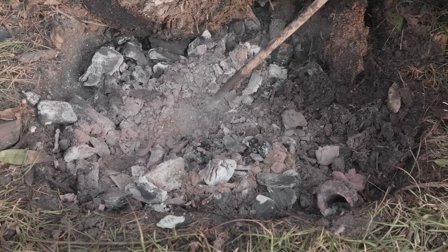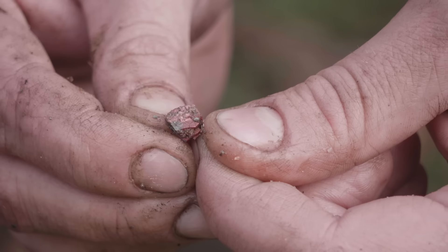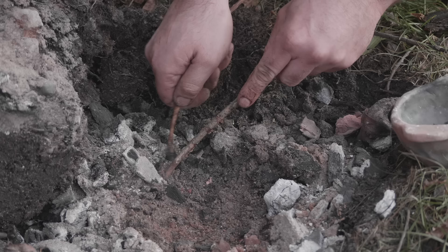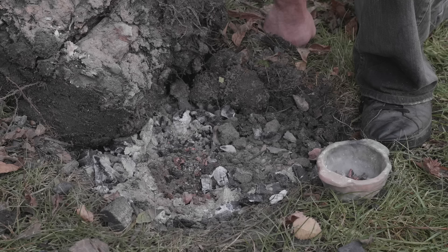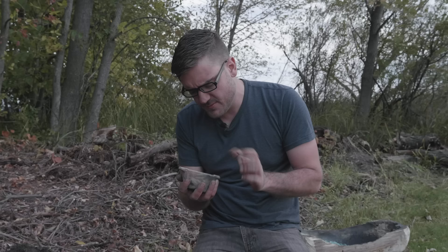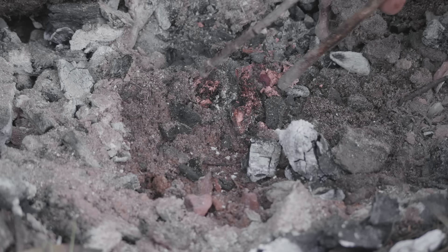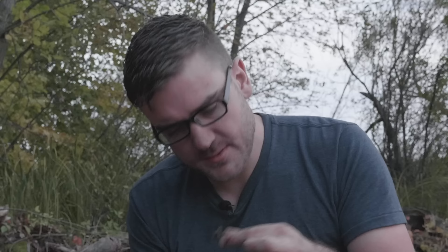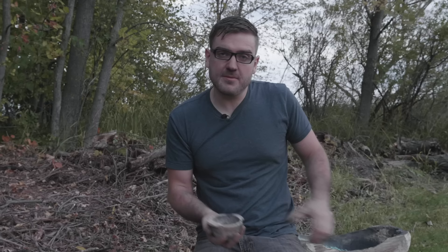Look at that — that is definitely metal. There's some more. Definitely copper — looks copper colored, it's definitely metal. Looks like a success. It's very pretty, there's a nice rainbow patina on it. That might be leftover malachite — might have been too big. That's very hot. It's weird that it kind of retained the shape of a rock. I think I've gotten the majority of the copper — looks like a lot of it has reacted. Some of it is kind of rock-shaped and pretty crumbly but looks like copper and has patina on it like copper. My suspicion is that it got hot enough to convert and reduce it, but didn't get hot enough to actually melt and form into a bead. I do have a few different prills where it obviously melted — it actually worked. It's the exact same process we did in England, over a charcoal kiln. Something this simple — actually kind of surprising. I'm going to keep picking through and get everything I can, then process the rest of the malachite.